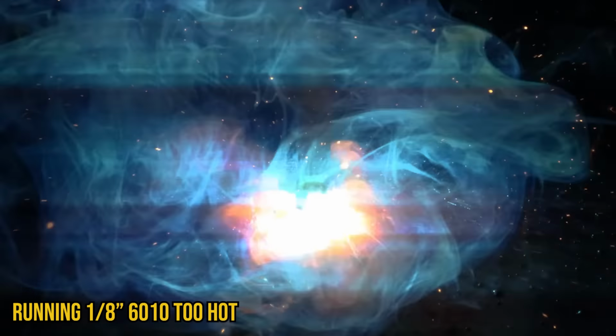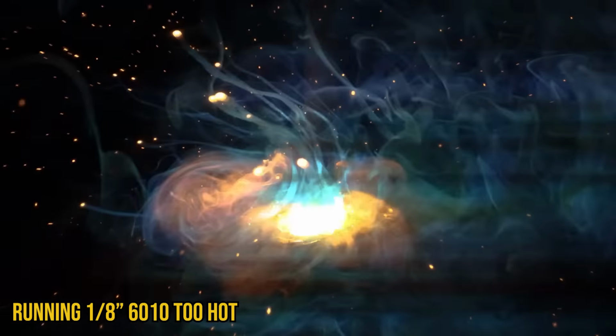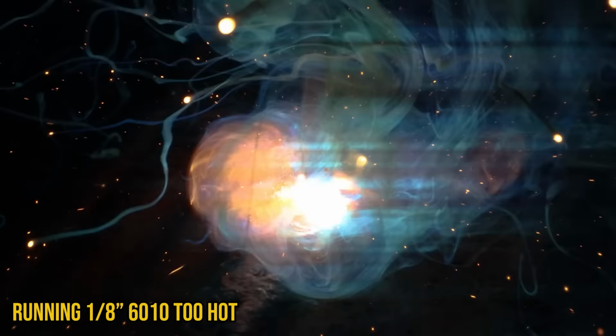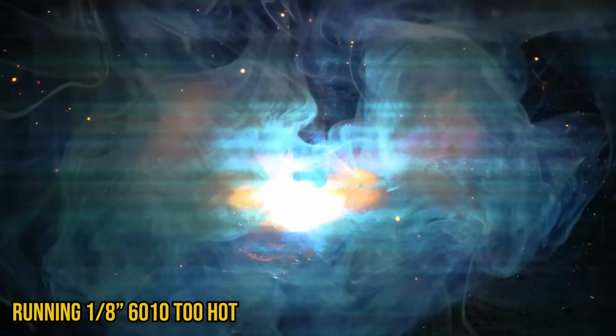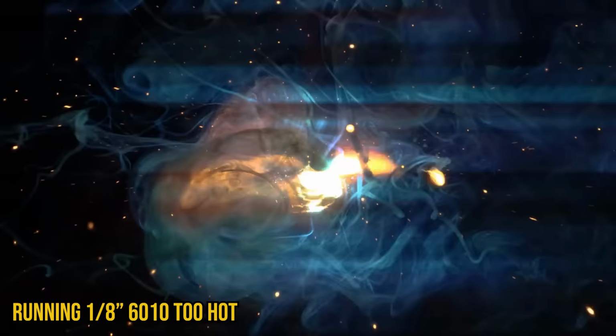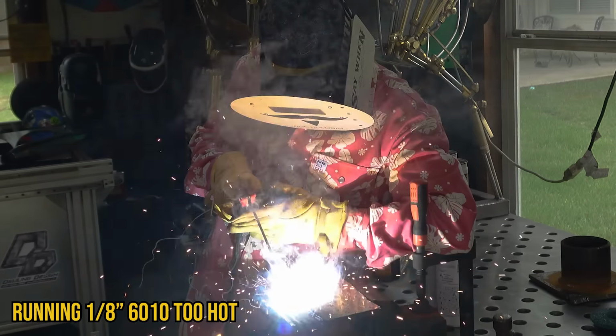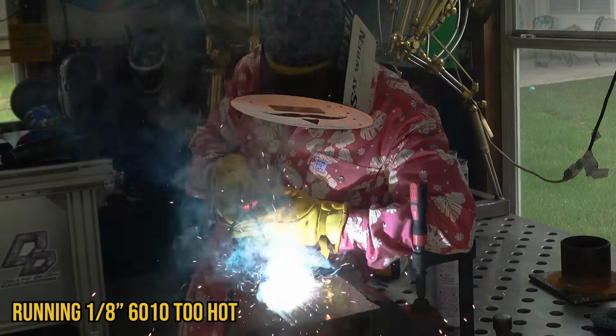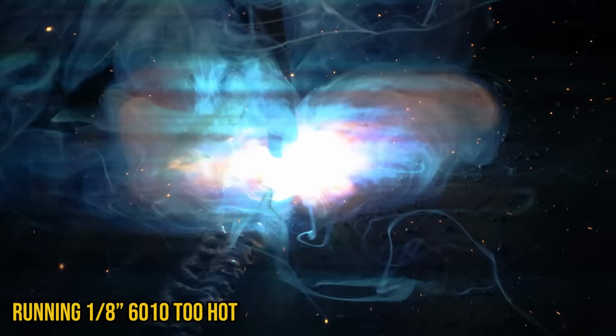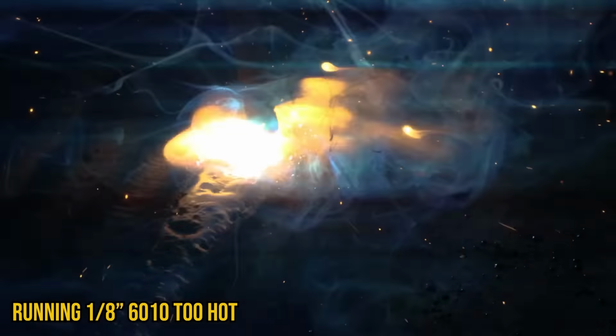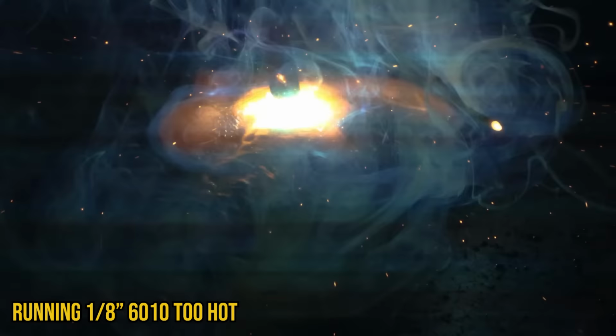You can see the puddle, maybe you can see the puddle. It's really elongated, and I can see that puddle is just digging. It's really deep. Now again, in the flat position, there's a lot of forgiveness. You put either one of these electrodes that are all position rods at this amperage in a different position, like vertical or overhead or even horizontal, you're going to see some huge issues where gravity is pulling this bead because the puddle is so fluid. But in the flat position, again, this rod is performing really well, even at a higher amperage.